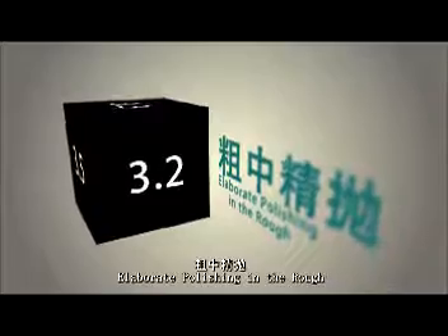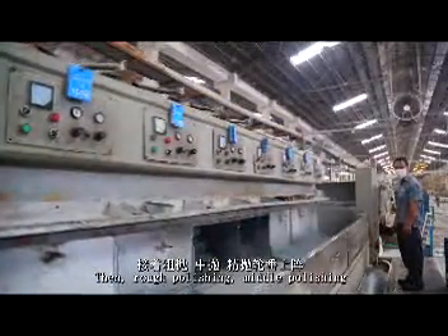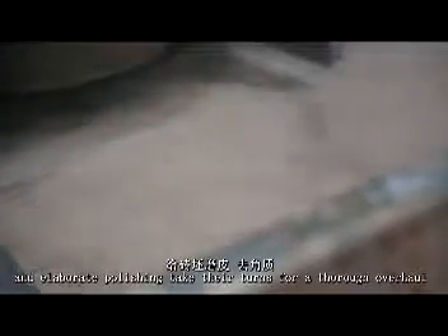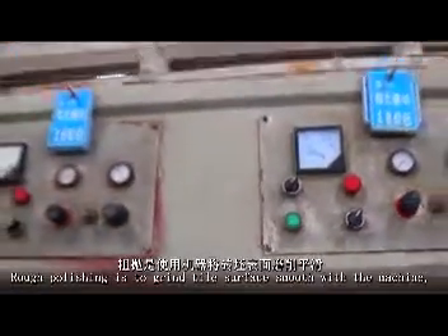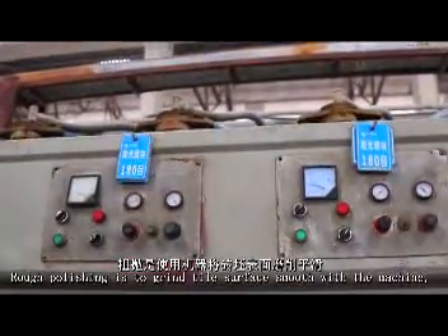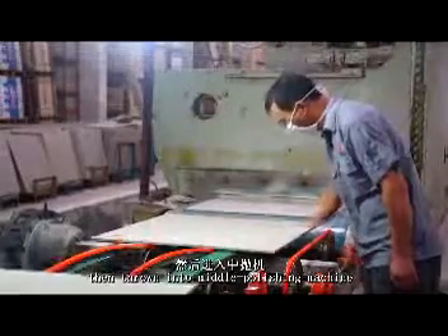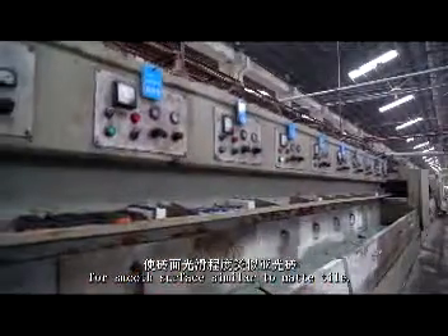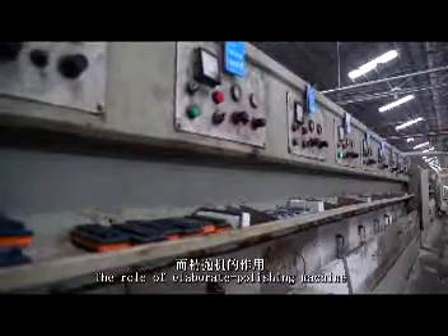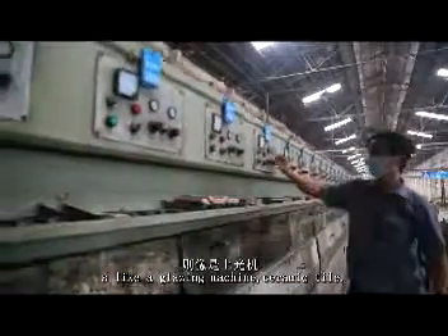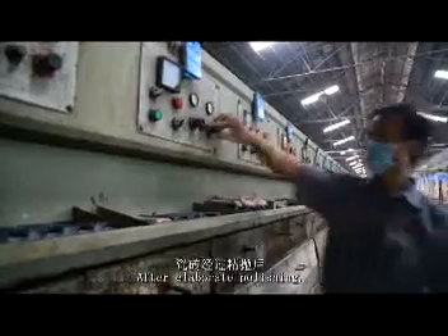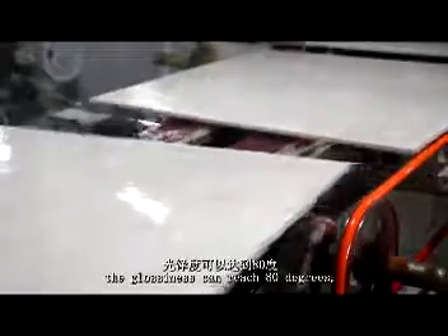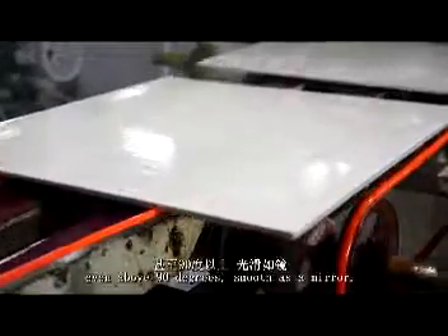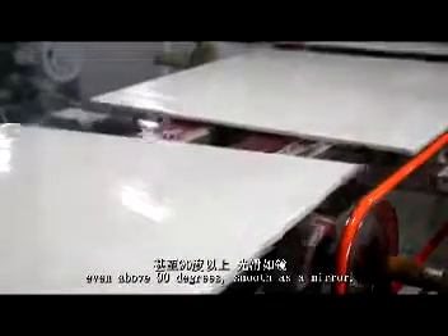Elaborate polishing in the rough. Then, rough polishing, middle polishing, and elaborate polishing take their turns for thorough overhaul after exfoliation and chamfer removal. Rough polishing is to grind the tile surface smooth with a machine, then it is thrown into the middle polishing machine for a smooth surface similar to matte tile. The role of the elaborate polishing machine is like a glazing machine for ceramic tile. After elaborate polishing, the glossiness can reach 80 degrees, even above 90 degrees, smooth as a mirror.